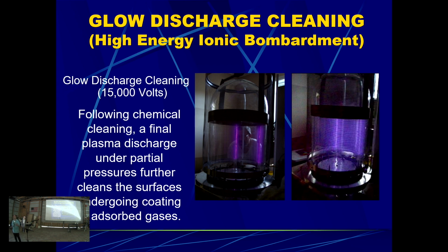That's contamination. We've got to remove that from the mirror, the glass, so that the coating can better stick to it. And so what we do is we bombard it with ions caused by the glow. So my big machine is at 15,000 volts, and it ionizes the residual atmosphere, basically water vapor and nitrogen, and it just basically molecularly sandblasts the surface of the glass, and it knocks off those adsorbed water molecules that are just stubborn things that want to stick to anything.